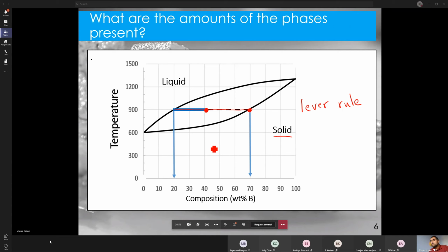So the lever rule might seem counterintuitive. What it asks you to do is, if you want the amount of solid, which is over here, you take this distance here. You take the distance from the overall composition to the liquid, this distance. Okay, let's call this distance x. You take x and you divide it by the total distance between the solid and the liquid. You divide it by this total distance. So if that total distance is y, we do x over y. That would be the amount of solid. So in our example here, x, the distance from 40% to 20%, is 20.